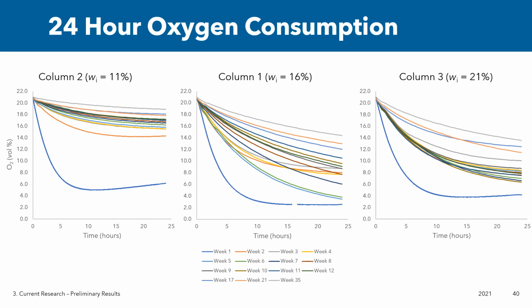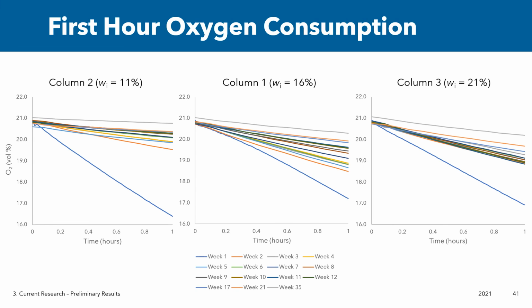The oxygen consumption slows dramatically after the first test, which may be caused by passivation of pyrrhotite. Looking more closely at the first hour of oxygen consumption can indicate the initial sulfide oxidation rate. Column 2 shows the highest rate of decrease in the first test, but a much lower rate for every test following. In column 2, the rates have only declined as time has progressed, but in columns 1 and 3, the rates have increased for a week or period of weeks and then decreased again.